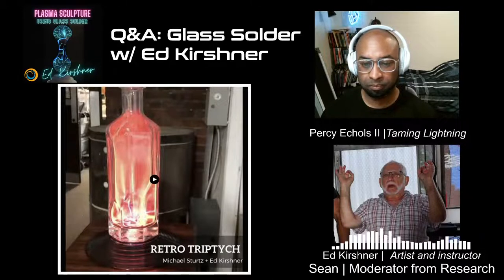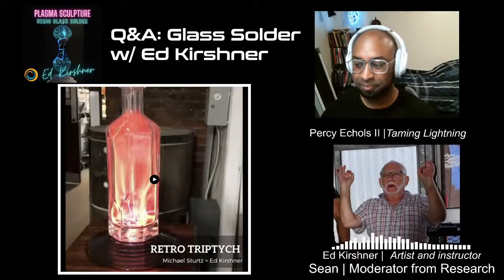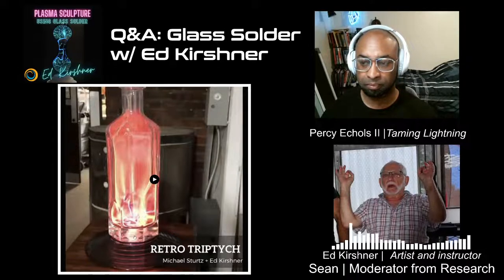The bottom, I had to put an electrode in, and you notice how thick that is. Even if it was the same glass, thickness to thinness is also difficult. Sometimes color is difficult. Even if two glasses are the same thickness and the same glass, if one's, let's say, cobalt blue and the other's clear, you could have an incompatibility. So you have to be careful with that.